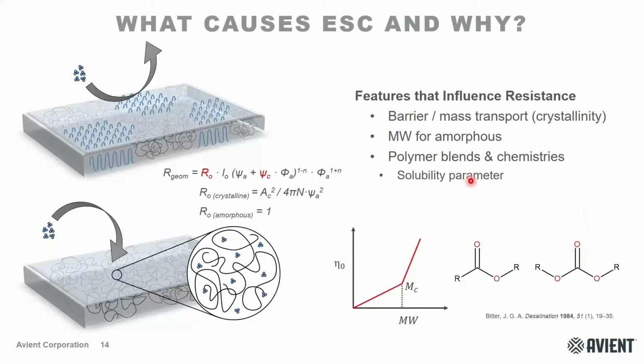And so if you're looking at this system of equations here, what this is essentially showing you is the diffusion resistance for a material. And in an amorphous material, the R0 is just normalized to 1. Whereas in a semi-crystalline material, you take into account the surface area of the crystallites divided by the number of amorphous channels and the volume fraction of amorphous channels. So in the total equation for diffusion resistance in a semi-crystalline material, you're adding the surface area of the crystallites as well as the volume fraction of the crystallinity. So what that means is the larger the crystals and the more crystals that you have in your sample, the better the diffusion resistance is.